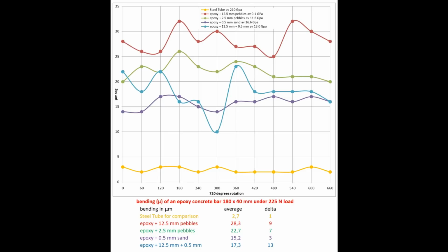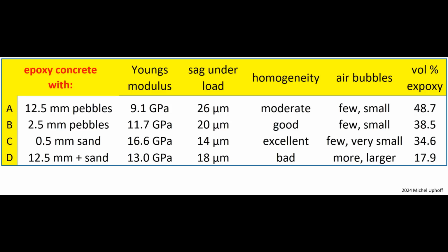But if dimensional stability, homogeneity, and reliability are a prerequisite, then it is better to opt for double the epoxy price of the excellently castable mixture of fine sand and epoxy resin. And in any case, choose an epoxy that hardens as slowly as possible, so that any air bubbles have time to rise. Also, never make uneven and unreliable mixtures of stones, huge pebbles, sand, and other materials, as I saw on some YouTube videos.